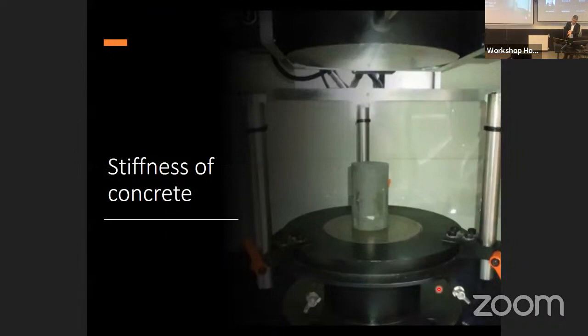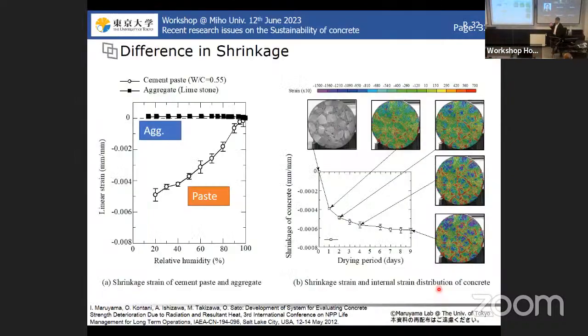So then I move to the stiffness of the concrete. Generally aggregate doesn't shrink, but there is some range. And if we use the limestone aggregate, by using the digital image correlation method, in the case of a water to cement ratio of 0.55, which is a general ordinary water to cement ratio, the cement paste shrinkage is something like this. At 60% relative humidity, which is the average relative humidity in Japan, it attains 3,000 microstrain.